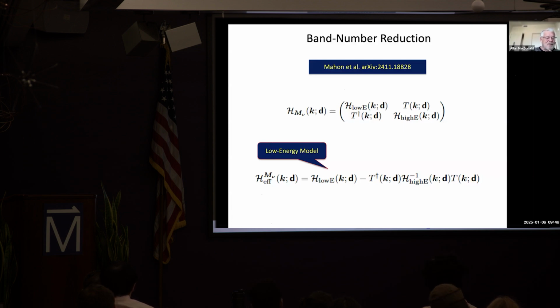And so if you follow this recipe, when you construct the Wannier functions, as many of you know, you're using states across the full band of the system. And so the number of bands that you need to include, which are kind of isolated for chemical reasons from other bands, might be bigger than the number of bands that actually are present at the low energies. So a simple example of that is the graphene and HBN case. If I have a tight binding model, the graphene is gapless, HBN is gapped, and so there's a big range of energy of interest where only the graphene orbitals are close to the Fermi energy.